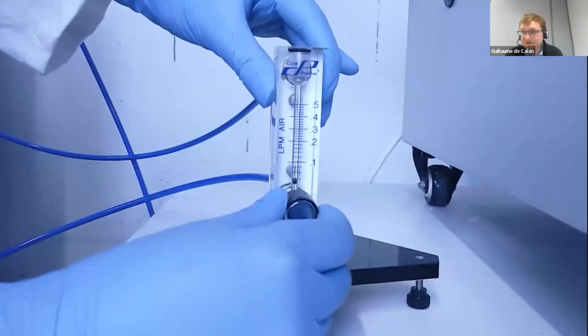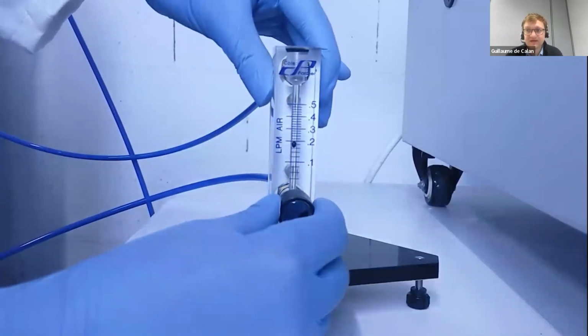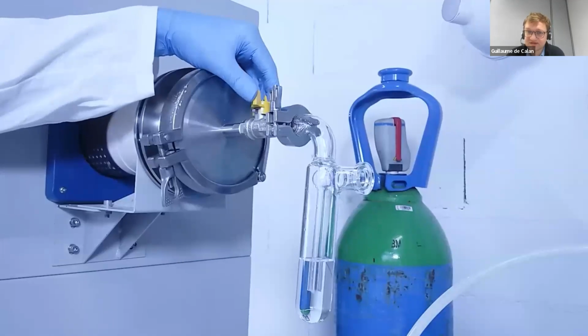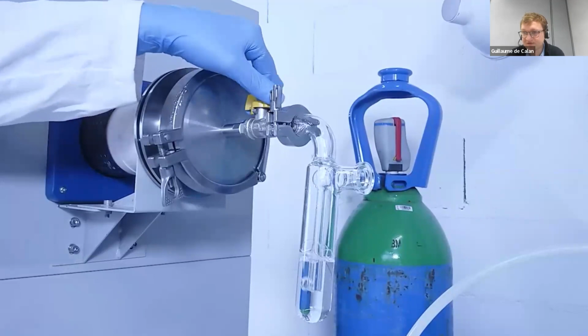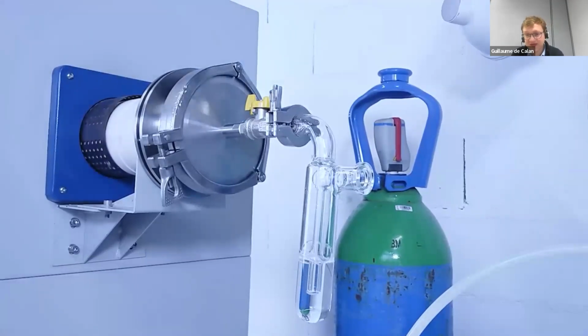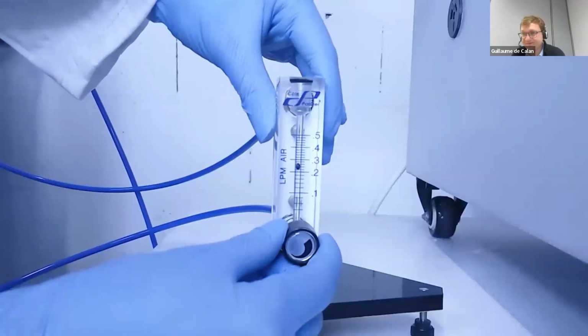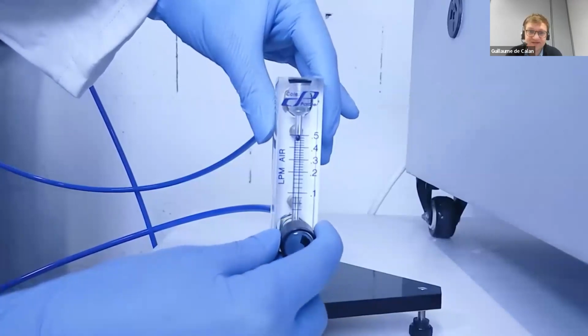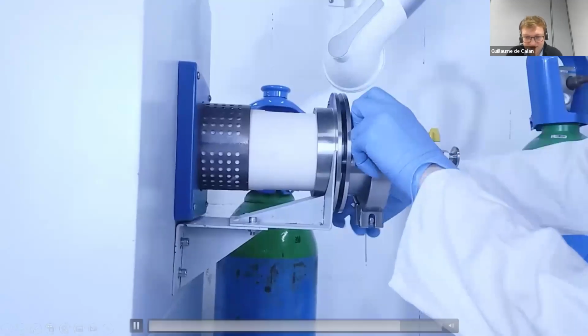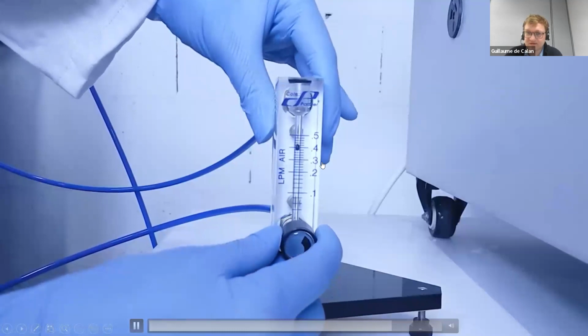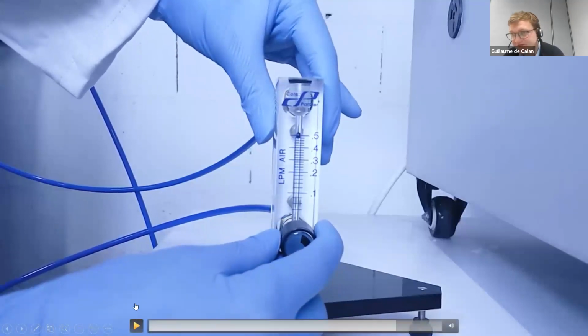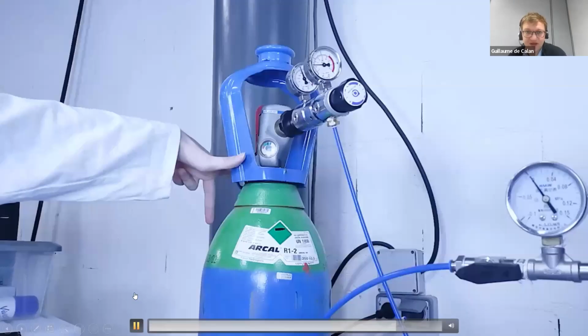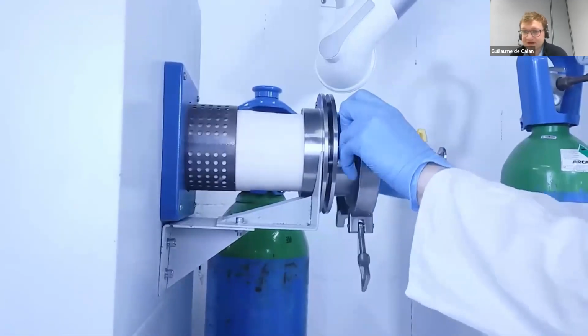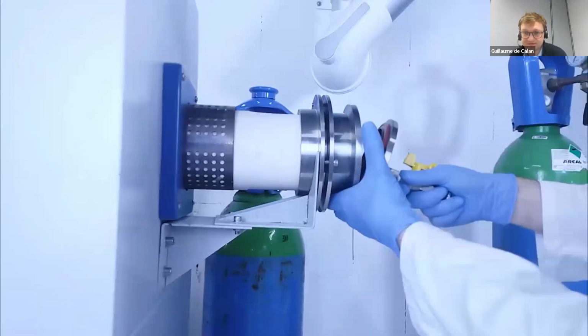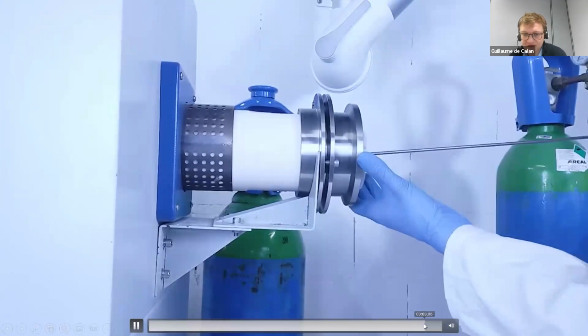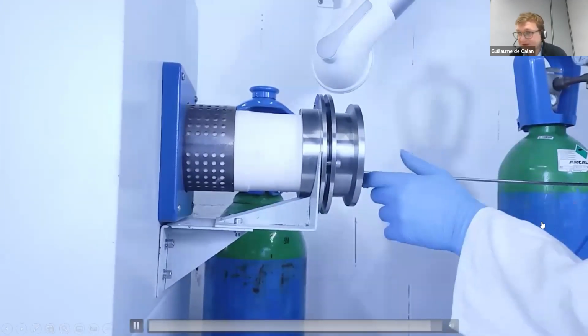You may think that just with the flow you can avoid having oxygen in the chamber, but having a completely neutral gas without any oxygen is difficult, and you really need that part to make sure you have the correct gas supply. And you can actually visualize the gas flow with the bubbles that are coming out of the bubbler. That does give you an indication, and then you can set up the precise value with the flow meter that will give you the number of liters per minute, and we do give recommendation for sintering our metal parts. At the end of it, you close the bottle, you open on one side, and you can remove your part. Again, that's very, very straightforward. You remove the heat blocks, and then you can remove the sintered part.